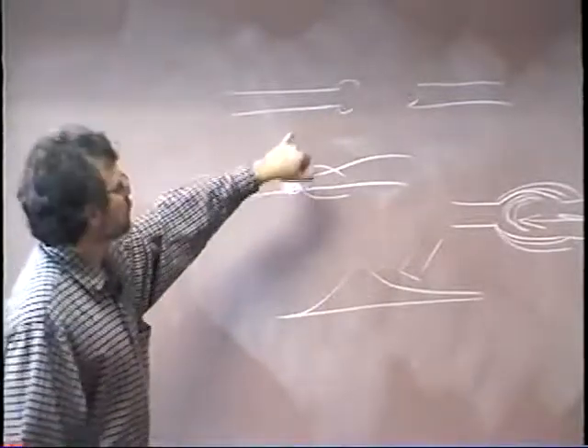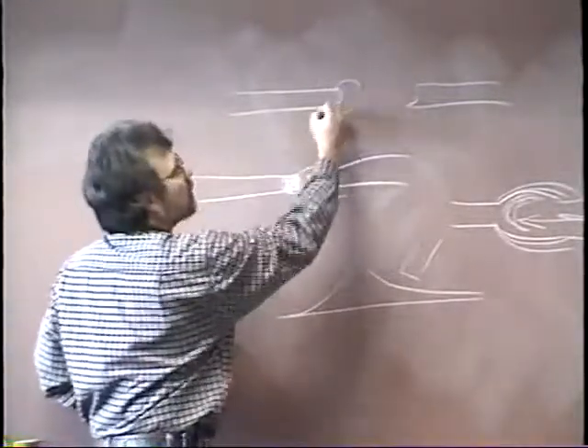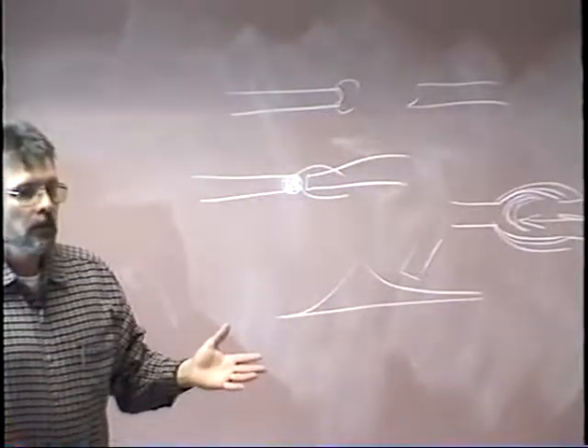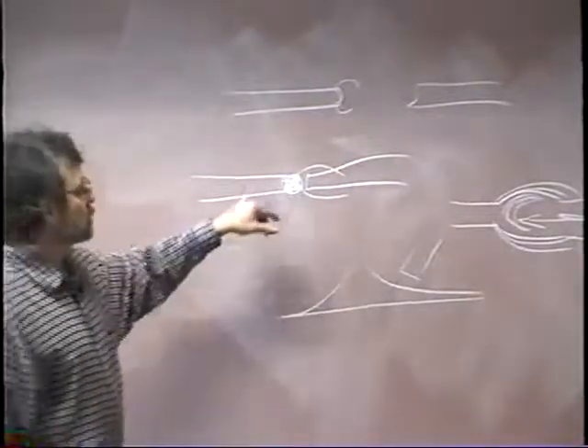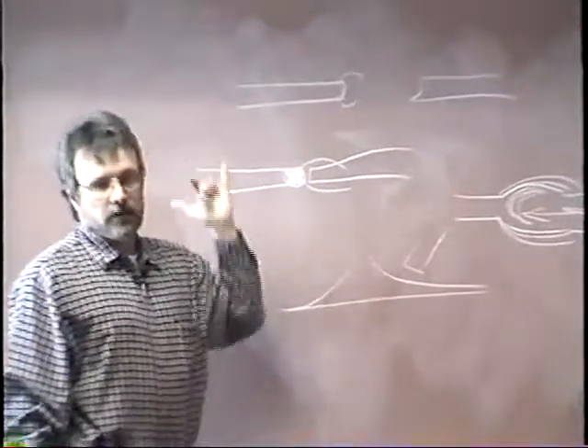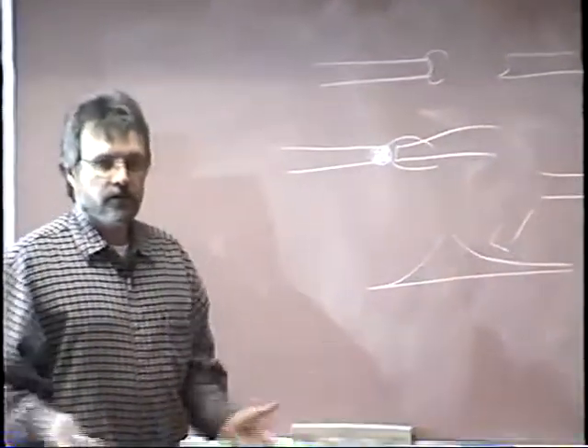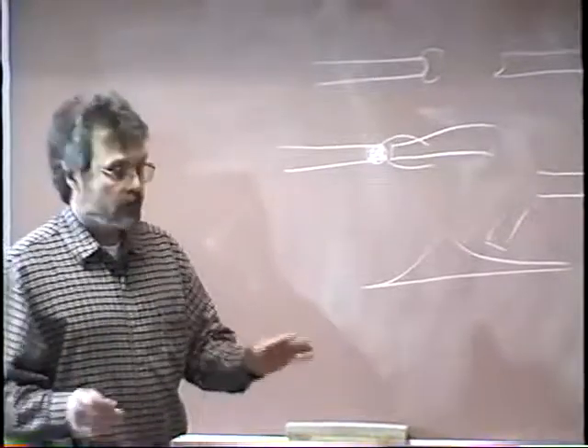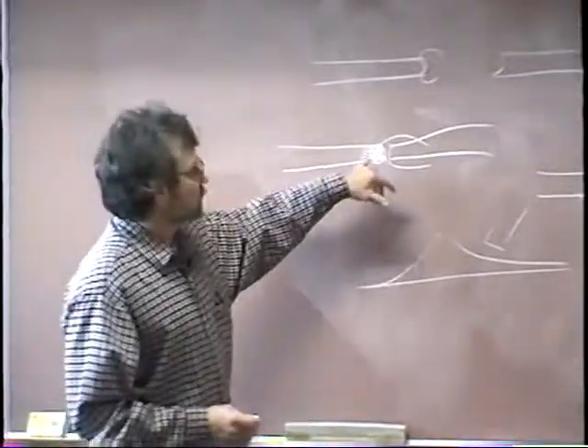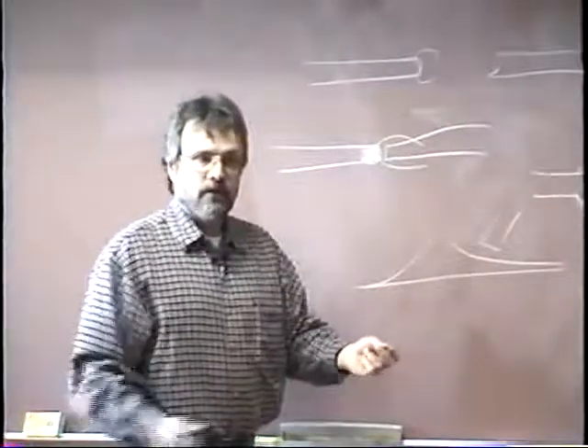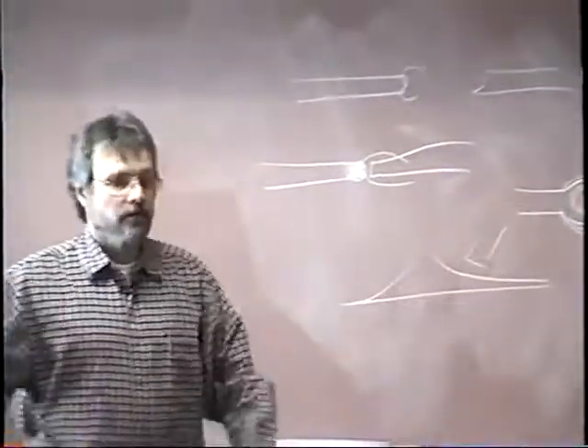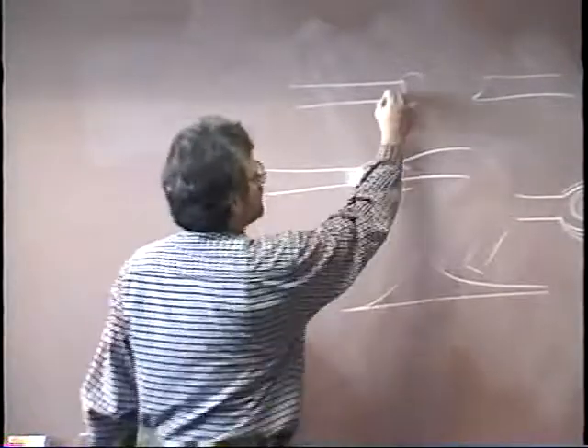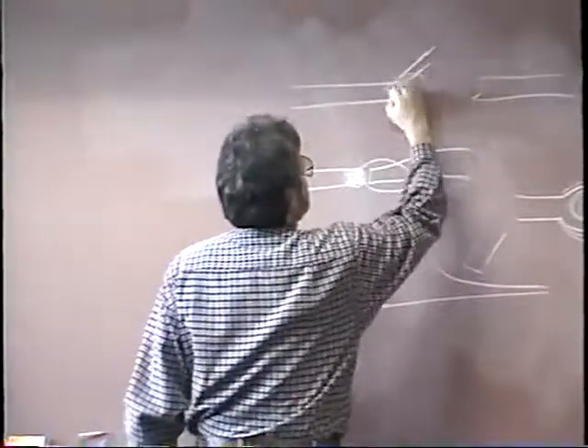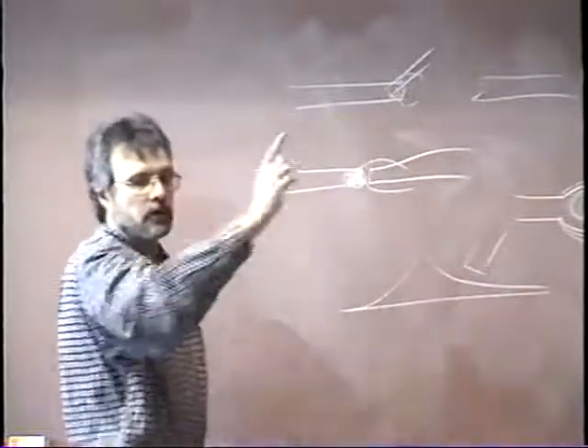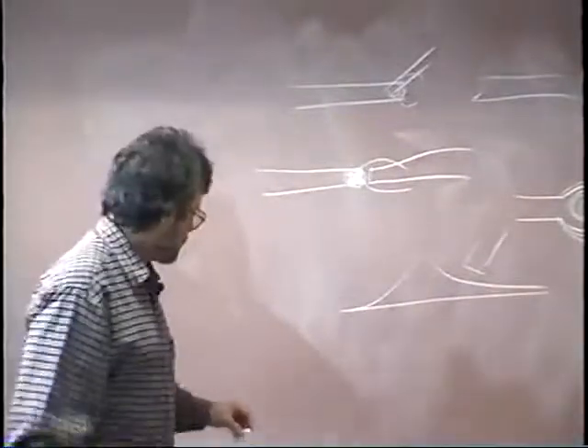When you open up your keyhole, that's when you use this technique. If you don't stop and regrind this, and a lot of times out in the field you won't. A lot of times if you're doing a production weld, you won't stop and feather the end of that off. Here in the class, that's fine. Feather it off, that's great. You know, there's not a problem with that. And if you have time to do it, feather it off. But out in the field, a lot of times you don't have time. You just got to grab another rod. Your helper's standing there handing you another rod. Then you use this technique where you strike back here 1/4 of an inch, remelt it, get down to that keyhole, and go on. So there's two techniques there that you have to use.